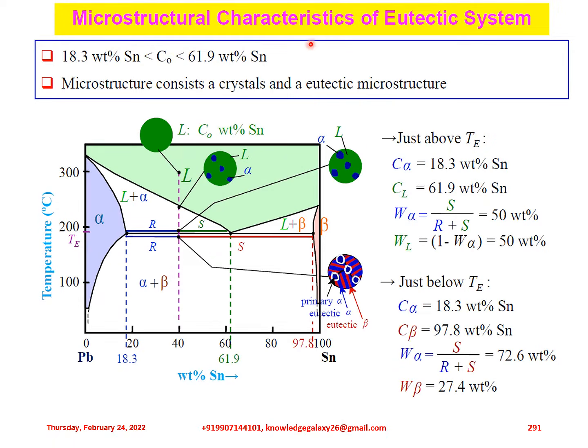So again, considering the microstructural characteristics of the eutectic system, we will consider 18.3 weight percent Sn, which is less than the 61.9 weight percent of tin. So the microstructure consists of alpha crystals and a eutectic microstructure. At this particular point the liquid has composition C0, that is, weight percent of tin, and where the solidus and liquidus start, L and alpha are present. These are different denominations, so let us describe them. Just above TE, that is, T eutectic, C alpha is 18.3 weight percent Sn, and C liquid is 61.9 weight percent Sn.